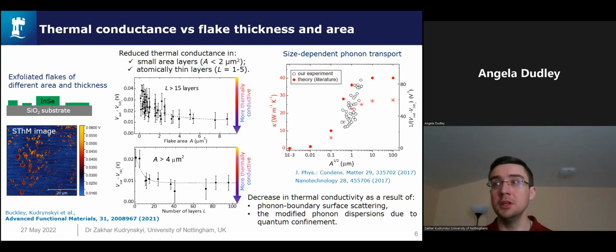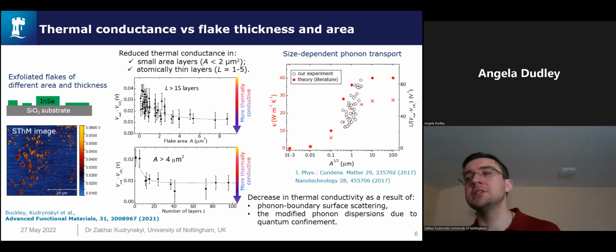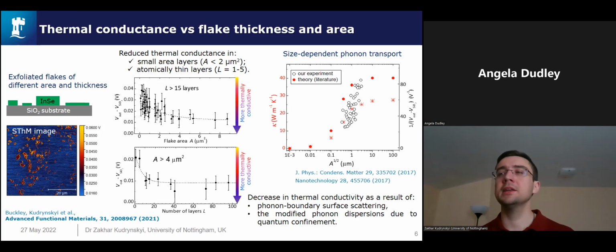This effect is quite anomalous and is experimentally reported for the first time, but is consistent with earlier theoretical studies. The graph here compares our experimental dependence of the thermal conductance on the flake area with calculated dependence from early theory work. And you can see that there is a good agreement here. We can explain this by taking into account size-dependent phonon transport, namely by attributing the observed effect to phonon boundary surface scattering and to the modified phonon dispersion due to quantum confinement.